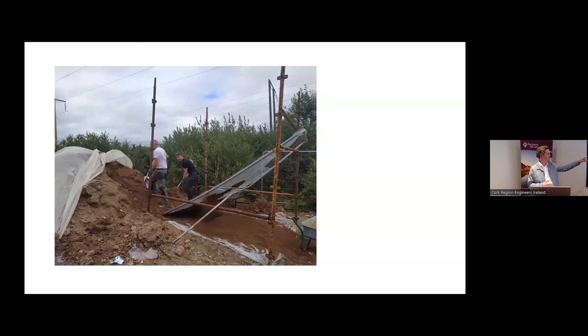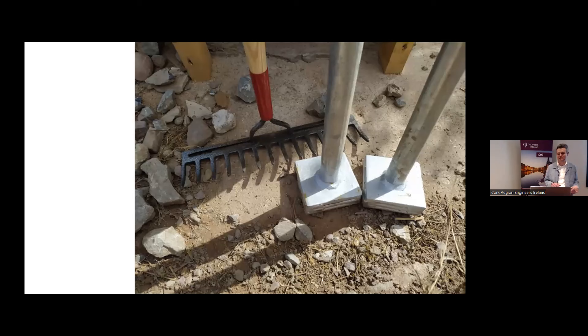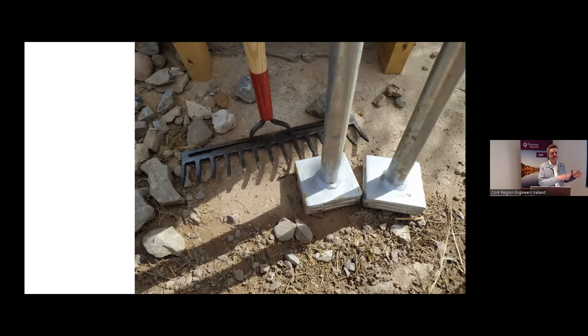Without plant machinery we had to be inventive, developing a grading system. Gerry, Daniel and Eamon were looking at different ways to grade the earth — I nicknamed the contraption 'the manger' because you'd put someone on it for a day and they didn't come back. When it's graded, the earth is incredible — almost like a beautiful sand. On the right are the rammers: 6kg is the optimum weight found historically, and a 100mm surface area plate has been found throughout history to be optimal. After doing this for six or seven hours on site, it has quite an impact.